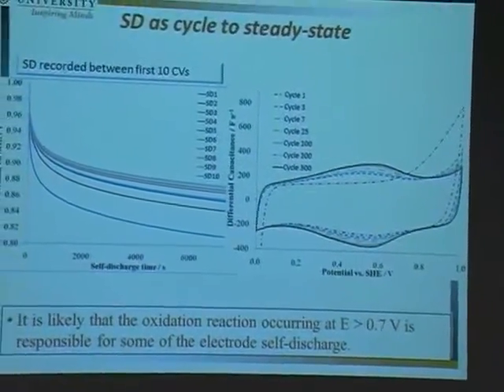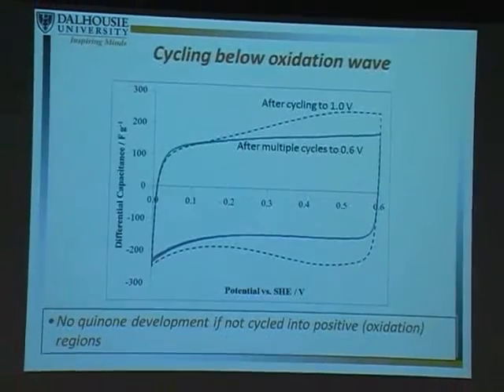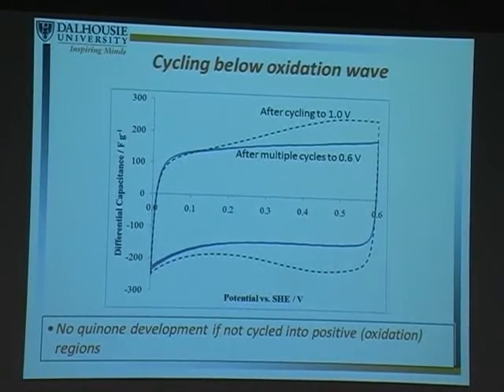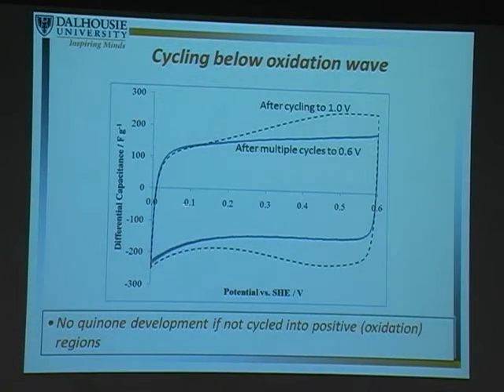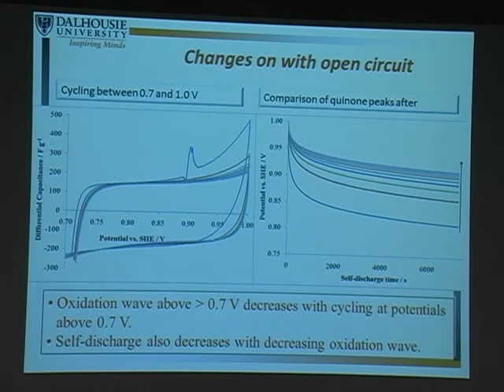So one of the things we did is we decided that if this oxidation wave is associated with the quinone peaks, then if we cycled only to about 0.6 V, we wouldn't do that oxidation, and then the quinones wouldn't develop. And so we did the experiment, we cycled between 0 and 0.6 for about 400 cycles, and in fact, we don't see any quinone peak development, which tells us that at least part of that oxidation wave is the development of the quinone. If we then cycle to 1 volt, as this is the same electrode, we see those quinone peaks develop. So part of that wave is the development of the quinone.